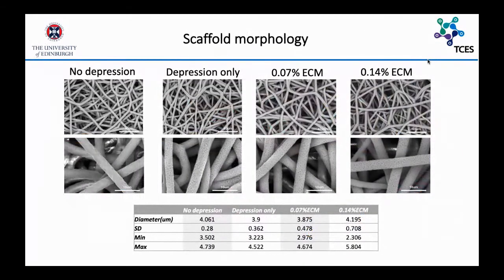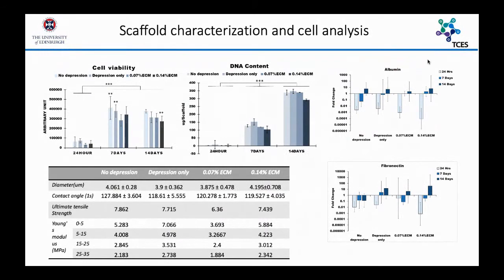Here are the four types of scaffold I made: no depression, depression only, and the scaffold with a set amount of ECM. The mechanical testing shows those scaffolds have very similar mechanical properties, and we also did different cell analyses, like the cell viability, DNA content, and the typical gene expression. The results show differences between the scaffolds and also between the time points.